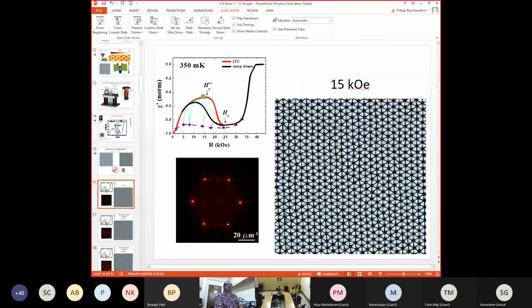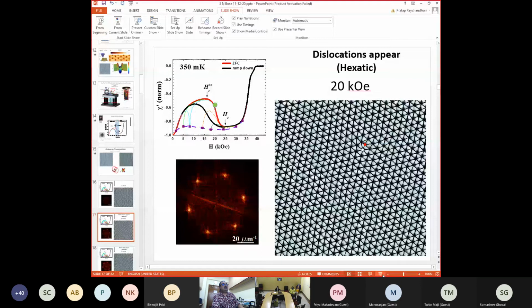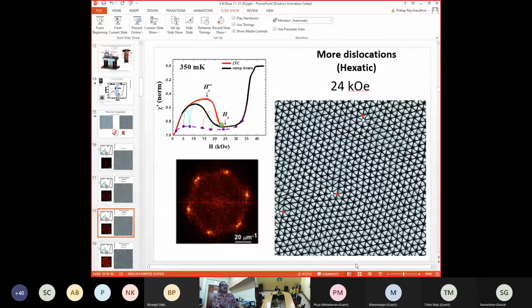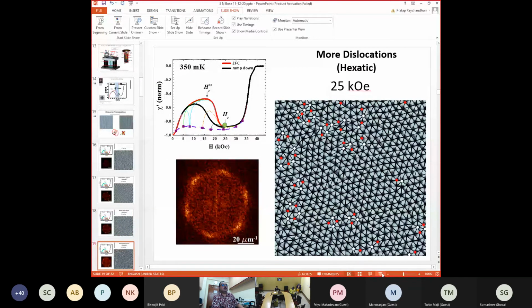I will start with 15 kOe state here, which is before the melting, before the order disorder transition starts. So here I have a nice vortex lattice. If I take a Fourier transform, I have 6 sharp spots, and there is no topological defect. I go to slightly higher field. Here I cross this onset field, and I start seeing dislocations. When I have dislocations, I still have the orientational order, as I have explained to you before, but the Bragg spots get broader, and then the Bragg spots get even broader, and then even broader, and that is when I have reached these 20, I'm close to 25 kOe there.